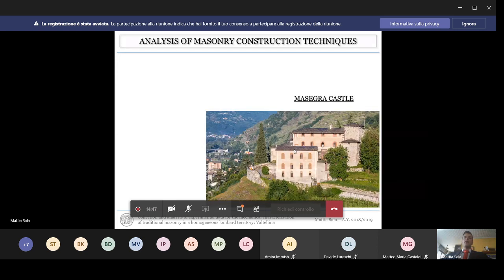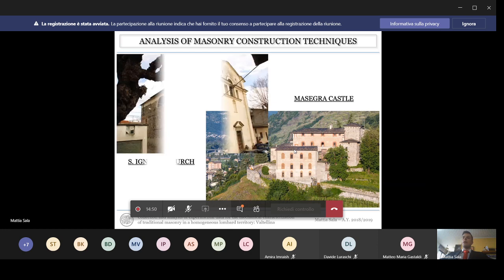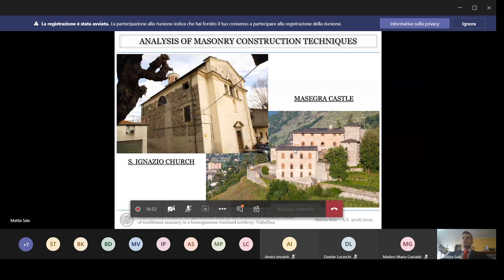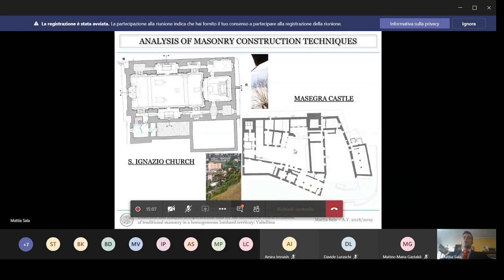To deepen the analysis regarding the construction techniques, I have analyzed 2 case histories, which are the Masegra Castle in Sondrio and the Sant'Ignazio Church in Ponte Valtellina. For both of them, historical and material analyses were performed, and also corings on both foundation and elevation walls, and mechanical properties analysis. And some points are stated. The materials are from a strictly local origin, with a prevalence of metamorphic rocks. There is a scarcity of use of mortar. The masonry of Sant'Ignazio Church was built mainly with a disordered texture, while the ones of Masegra Castle are both with a disordered texture and with rather horizontal courses. And the mechanical properties will be discussed in the next points.